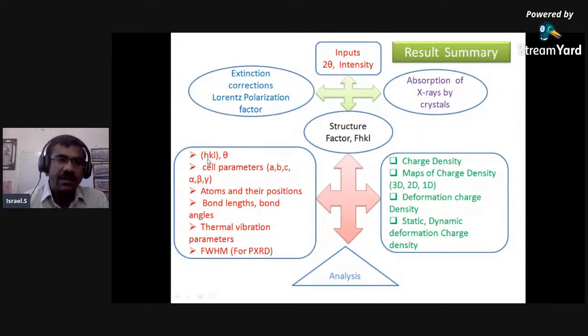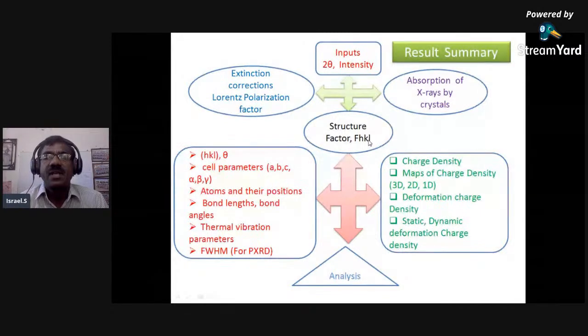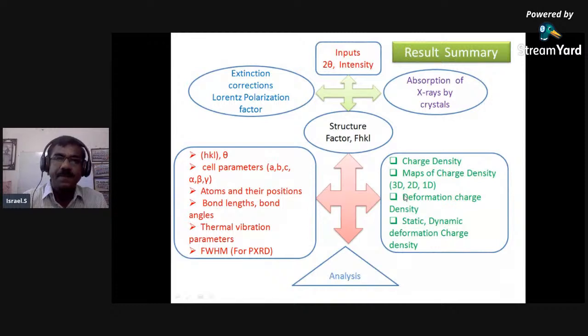You'll get the index, the planes which obeyed Bragg's law, theta, the scattering angle, cell parameters a, b, c, alpha, beta, gamma, atoms, their positions, bond lengths, angles, and thermal vibration parameters. In the case of powder XRD, you'll get one piece of information from the full width half maximum, which is useful in determining the size of the particle. Once you convert to the structure factor using Fourier transform techniques, you can go for charge density. Once you get the charge density, there are many other things you can understand from the analysis. We'll talk about all these things in the coming session.